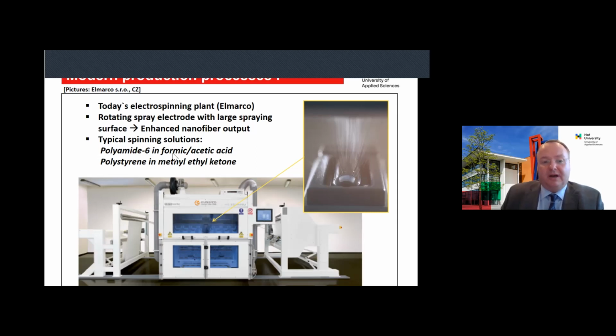For instance, polyamide 6 is often used, dissolved in formic acid or in a mixture of formic acid and acetic acid. And polystyrene is also possible to use, applied from a solution in methyl ethyl ketone. And that is a typical, more or less industrial scale, a small industrial scale plant for the coating of substrates, nonwovens or cellulose materials, with nanofibers.